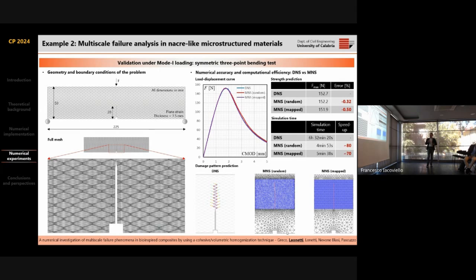So, for mode 1 loading, these are the results. Also in this case, very, very small error on the peak, less than 1%, and very high values of the speed-up, 80 times faster analysis.